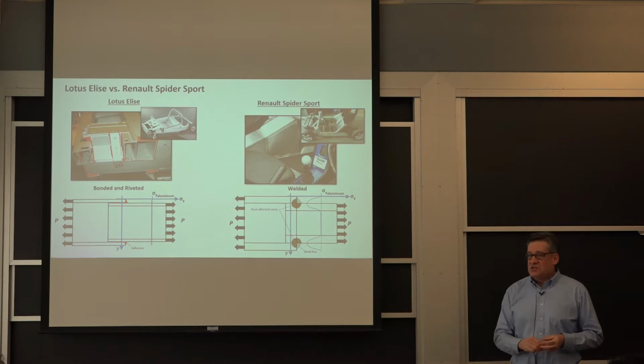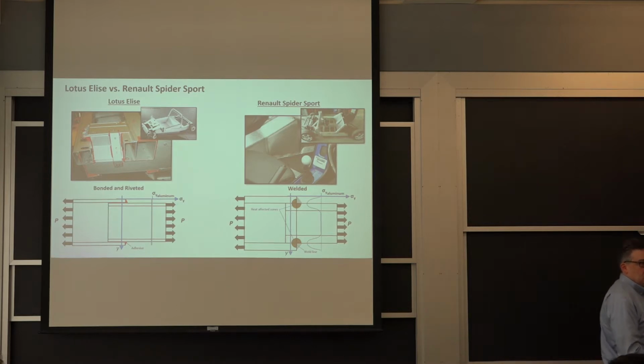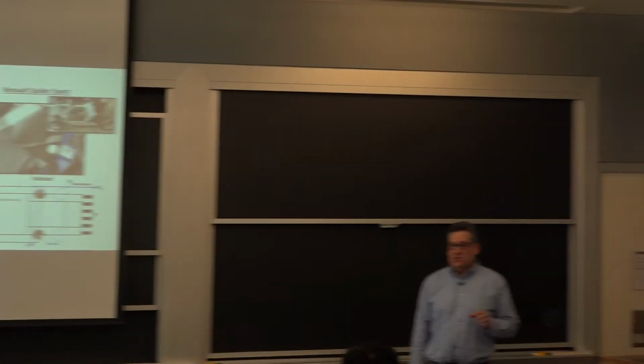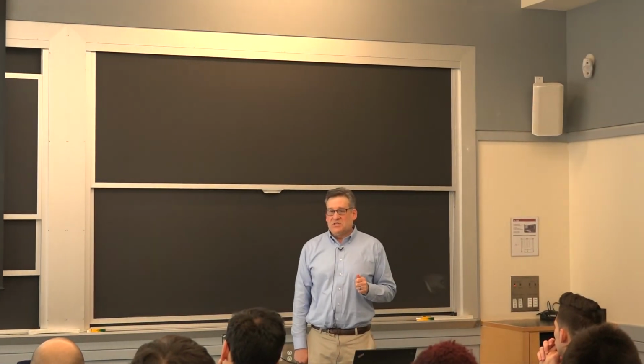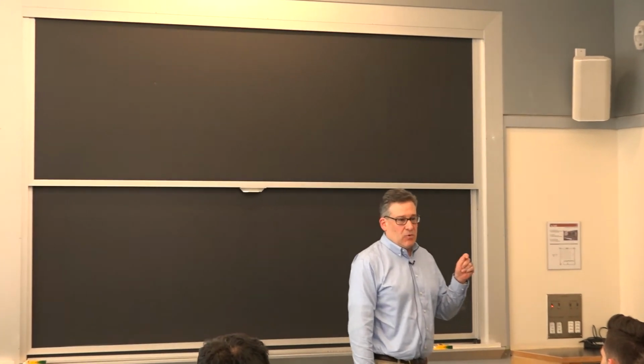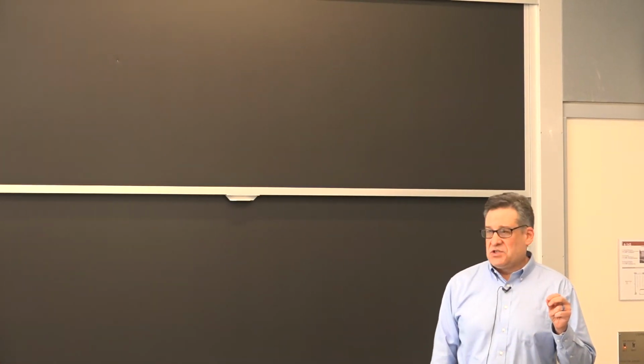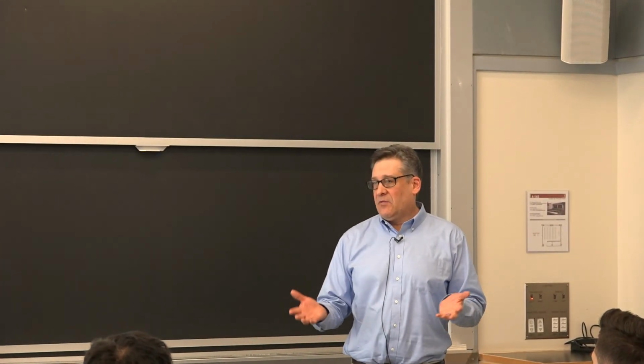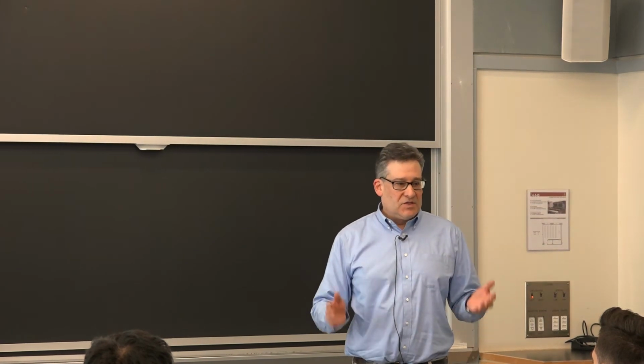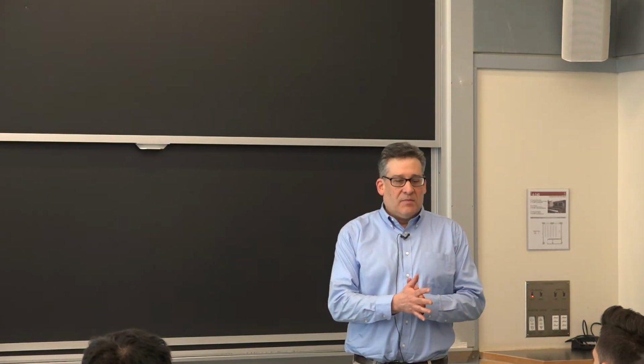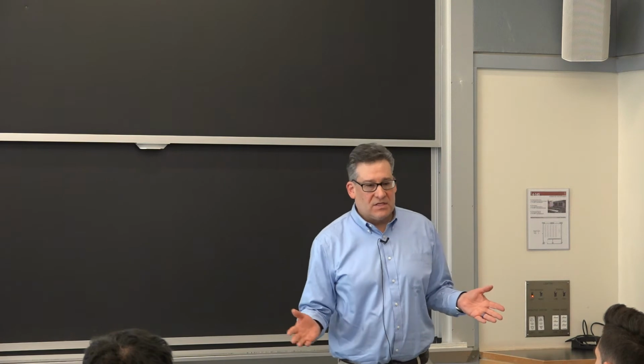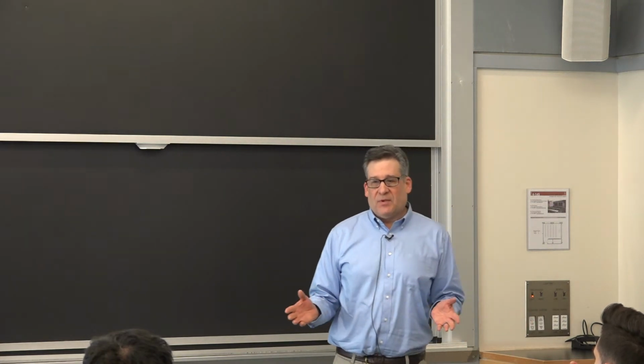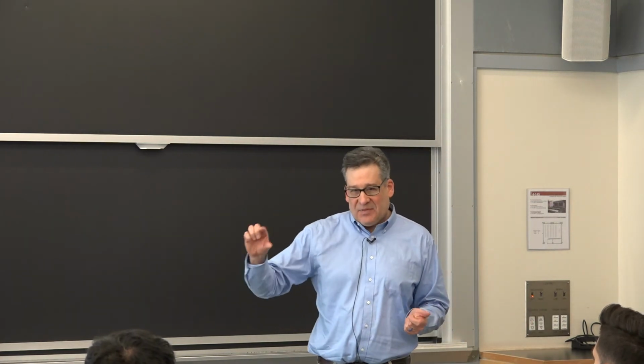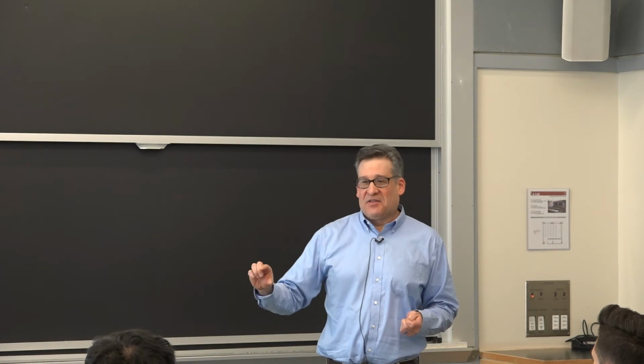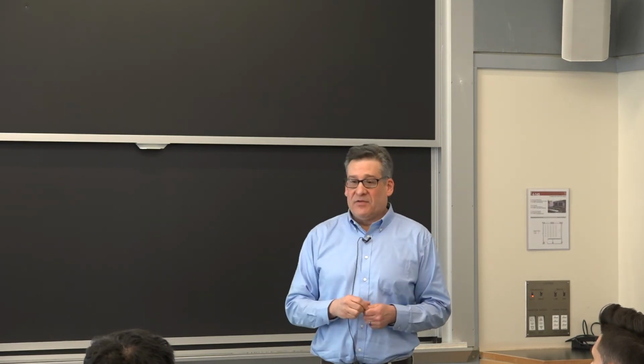Because of that difference in strength, the Renault engineers had to use much thicker wall thicknesses on those extrusions in order to get sufficient strength out of that joint. The Lotus engineers could go with a much thinner wall because they weren't going to lose anything. Now, unfortunately, with extrusions, as things are today, you can't really go to variable wall thickness - you're sort of stuck with one wall thickness. So the whole structural member had to be dimensioned to compensate for that difference in strength. And that's why the car weighed 500 pounds more.